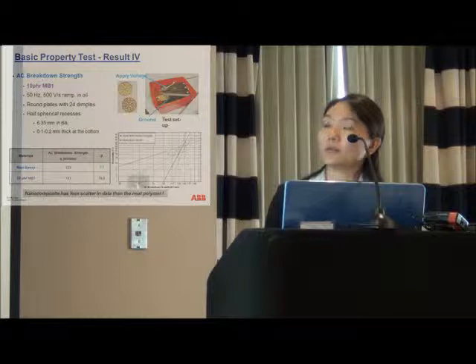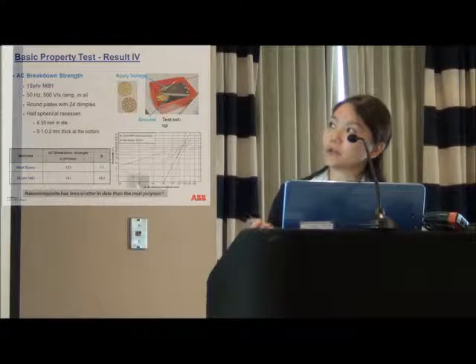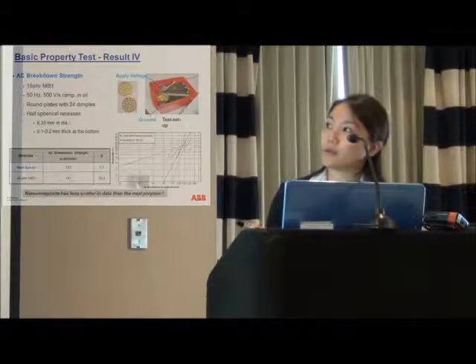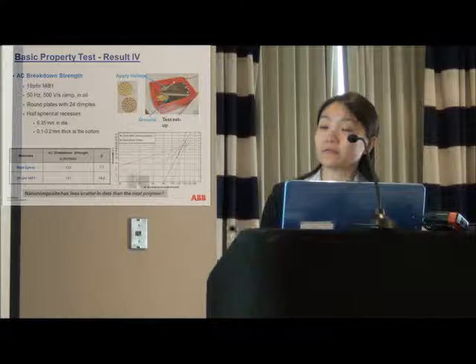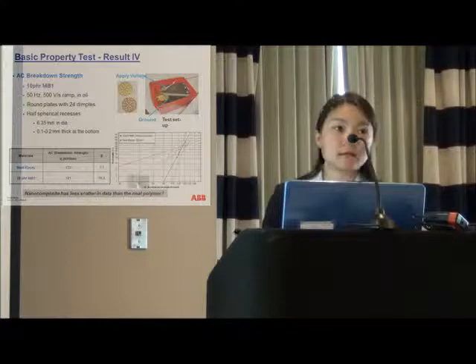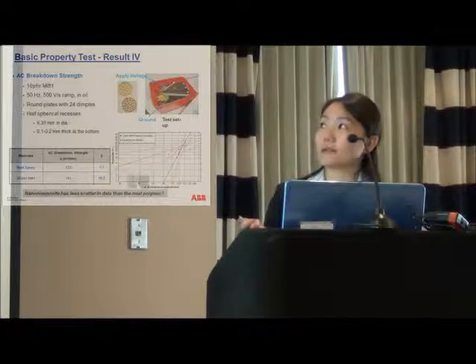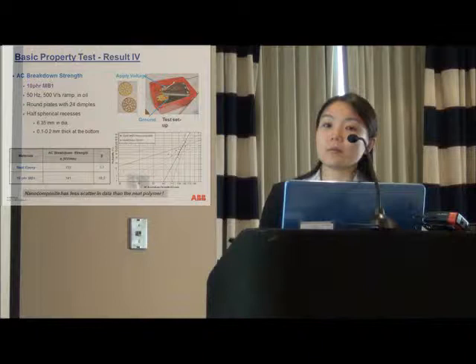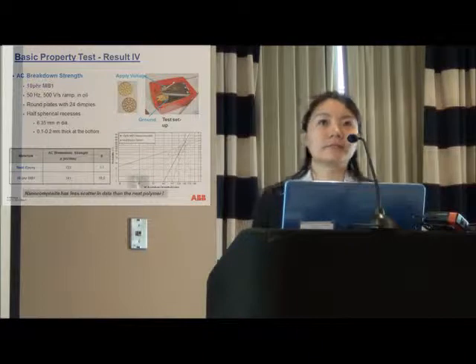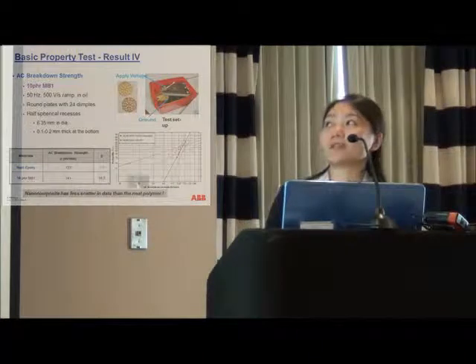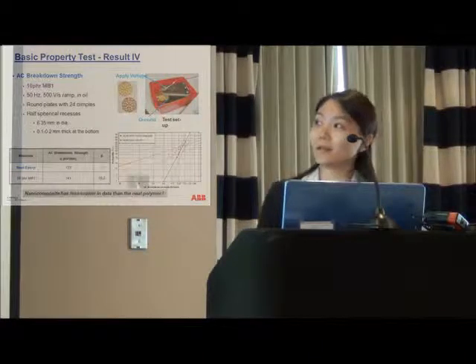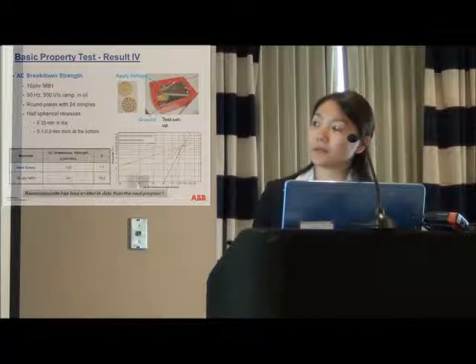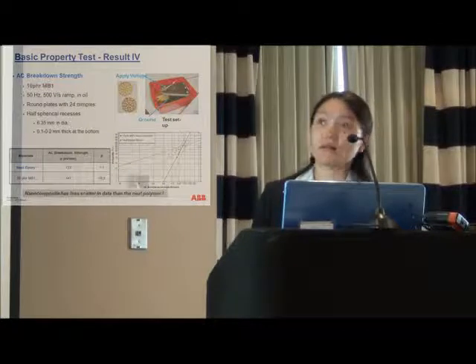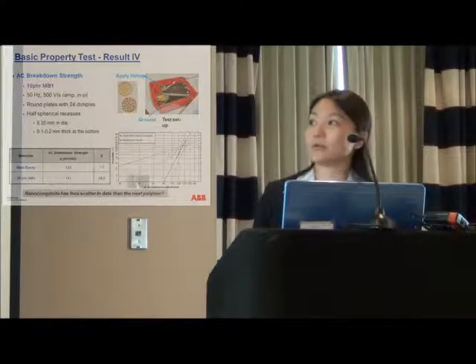Here we used this geometry: a rounded plate with 24 dimples or half-recesses. We tested it in oil. The top electrode is half-spherical and the bottom electrode is flat. The sample thickness at the tested location is about 0.1 to 0.2 millimeter.